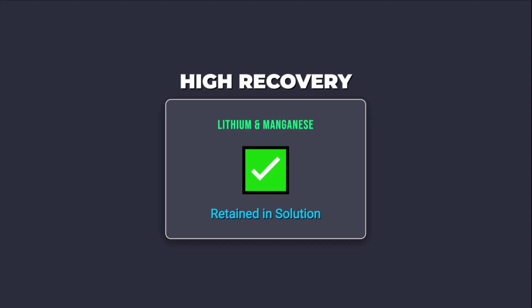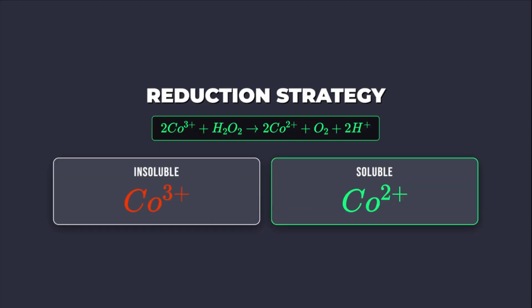Controlling the pH and redox potential is essential for maximizing the dissolution rate and minimizing the co-dissolution of impurities like iron and aluminum. The dissolution of the cathode material, for example, lithium cobalt oxide, requires a reducing agent because the transition metals are typically in a high oxidation state, such as cobalt 3+. Sulfuric acid alone is insufficient to dissolve cobalt 3+ efficiently. Common reducing agents include hydrogen peroxide or sodium sulfite.